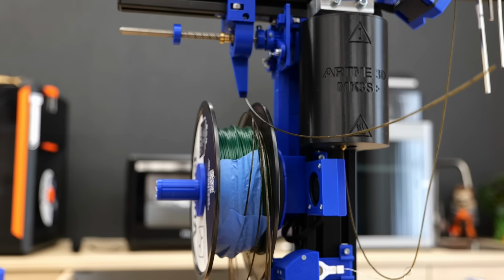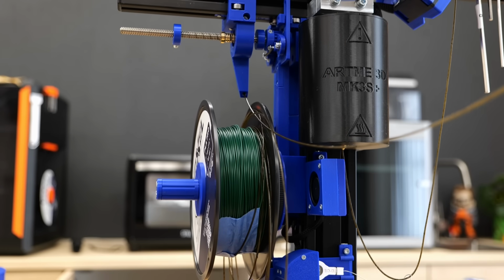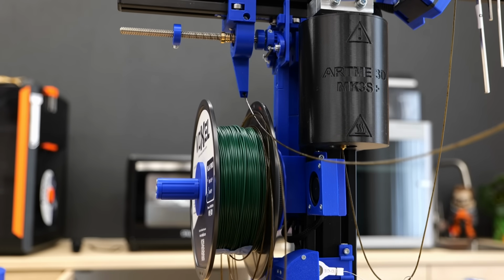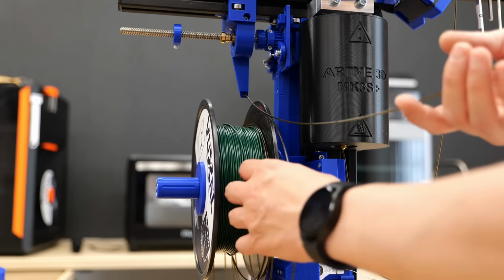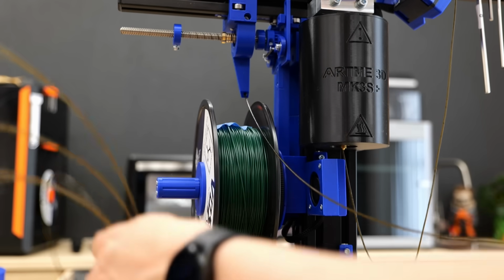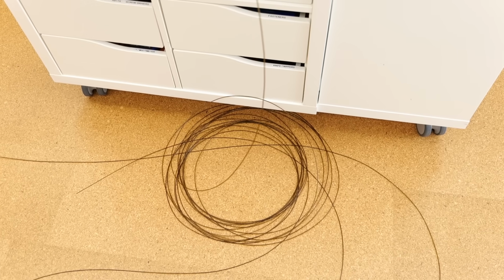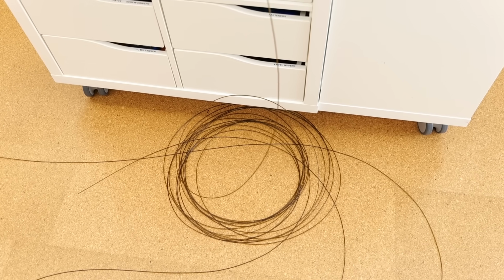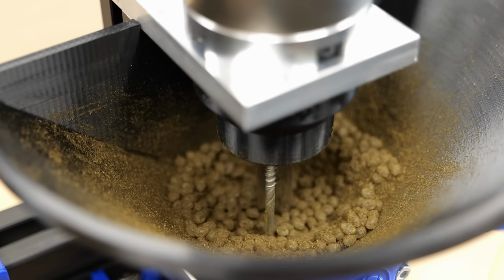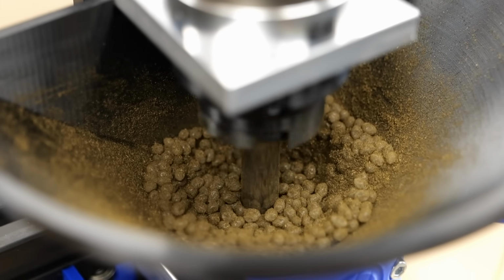Unfortunately, I was a bit overconfident with my solution to my breaking filament problem, because after some minutes the filament snapped again and caused everything that I had already spooled to unwind. So I gave up on the spooling idea for now and simply let the rest of the filament fall onto the floor. When the filament in the feeder got lower, I also noticed another issue.